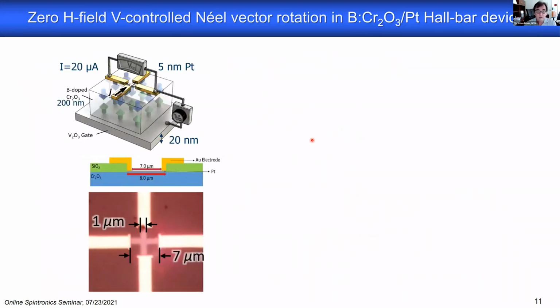So that's what we do now. Rather than using the pure chromia system, we use the boron doped chromia, but put it in the same type of Hall bar device. And notice also we are able to apply a voltage across the thin film of boron doped chromia, because we deposit this material on a gate electrode, in this case vanadium oxide, which is an oxide but metallic at this temperature. And so we can apply a voltage. Here you see the optical image of the resulting lithography of that Hall cross.